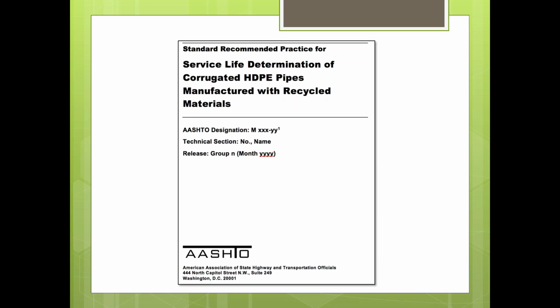One thing I do want to share as well is that from a quality standpoint, the amount of testing that's done currently on virgin resins will be significantly increased if you do decide to use recycled resins. The frequency at which we run the standard NCLS, carbon black, tensile strength testing, all of the testing that's done on virgin resin, when you use recycled resins, it will be exponentially increased, almost 30-fold in the amount of testing that we'll have to do on both pre-manufactured and post-manufactured product